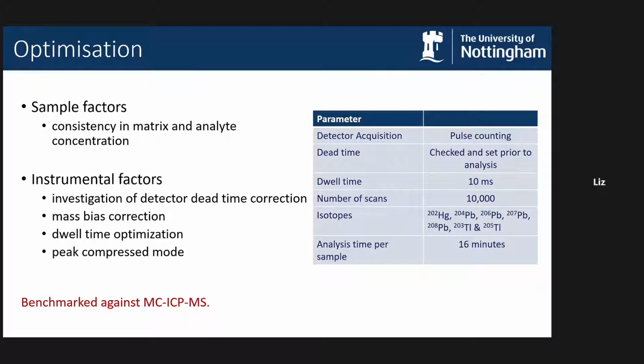So having measured total lead, we then did bespoke dilutions on each sample to bring the concentration to a near identical concentration of about 15 micrograms per litre. And that was below the point at which the detector would trip into analog mode, but as high as we could push it to maximise the signal of the lead-204 isotope. So by doing that, we were also reducing the effect of any error in the detector dead time correction.